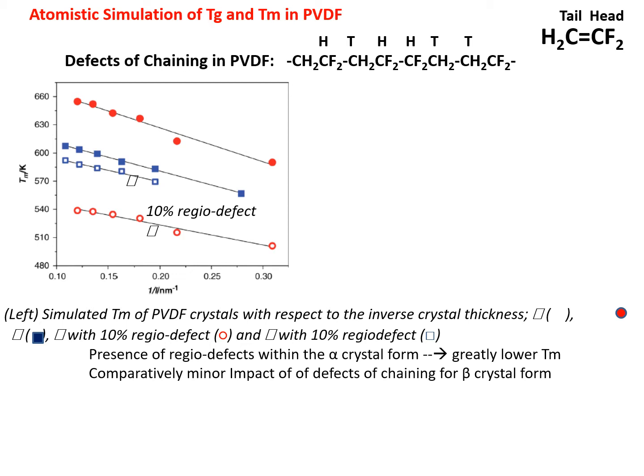And also, when you have 10% regio defects, so this is the alpha phase, okay, when you have simulated 100% head-to-tail addition. But when you see 10% defects, you have a dramatic effect on the loss of melting temperature, while for the beta polymorph, the influence of the presence of 10% regio defects is not so critical.